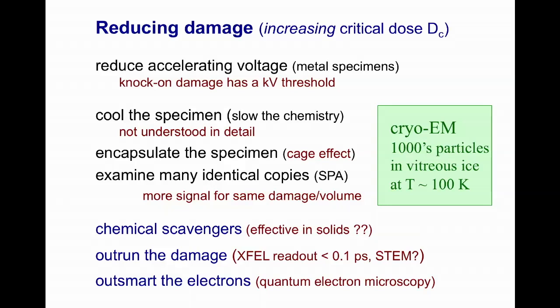In cryo-EM of biological specimens, the specimen temperature is reduced to around 100 Kelvin, reducing radiolysis by typically a factor of 5 to 10. In addition, biomolecules or viruses are encapsulated in vitreous ice, which helps to keep the atoms in place by what is often called a cage effect. Thirdly, the images of thousands of molecules are combined by computer software, which increases the signal level or spreads the damage over many molecules.